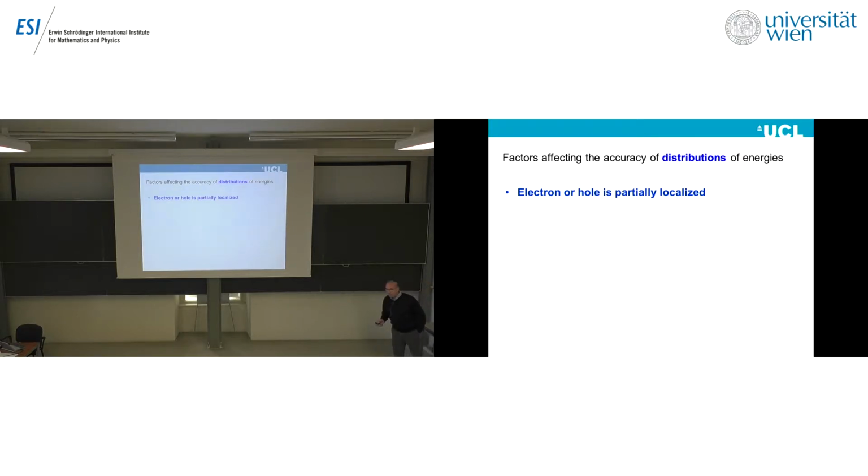So, on one hand, trapping energies are bigger. On the other hand, they are very strongly distributed. The amount of Hartree-Fock exchange is obviously an important factor, and I talked about that before. Different sample densities are another important feature for distributions, because when we produce these amorphous samples, they have different densities. They are produced using NPT ensembles, so they are allowed to expand, and then when we freeze them, they vary in size. So this also affects the distributions of these numbers I have been showing you, though not the qualitative features.